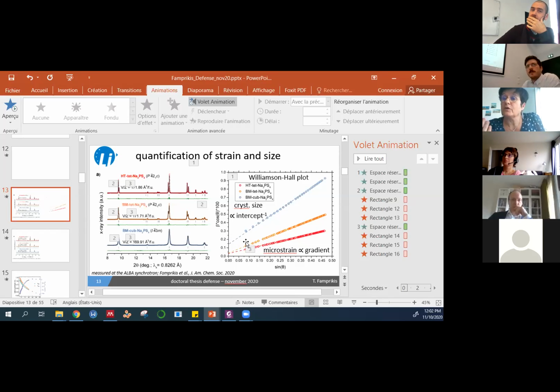I accepted it because you said that you had this microstructure effect. So here, when I came to this Williamson-Hall plot, I was a little bit surprised because I would have expected to see this microstructural effect. It means different data depending on the families of the crystallographic planes. And it is not obvious here. So my question is, how did you determine the broadening of the line to calculate this Williamson-Hall plot?